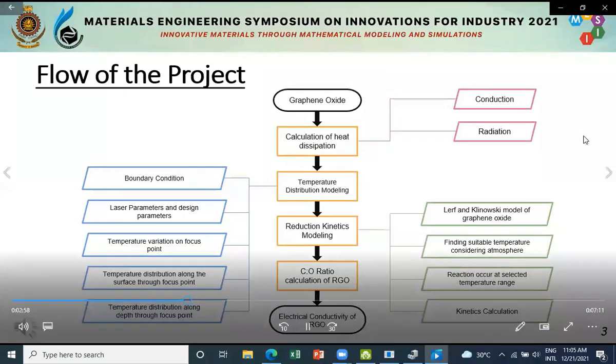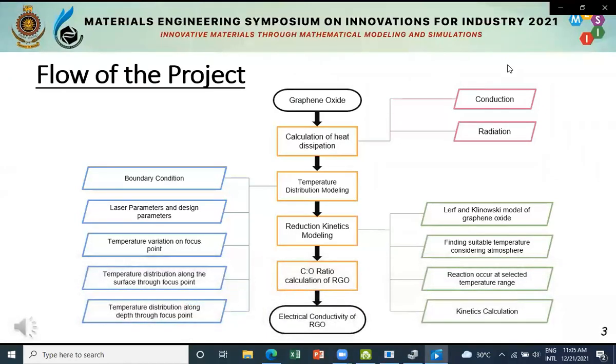With the results of kinetic calculations, we calculated the carbon to oxygen ratio in order to find the electrical conductivity of reduced graphene oxide.